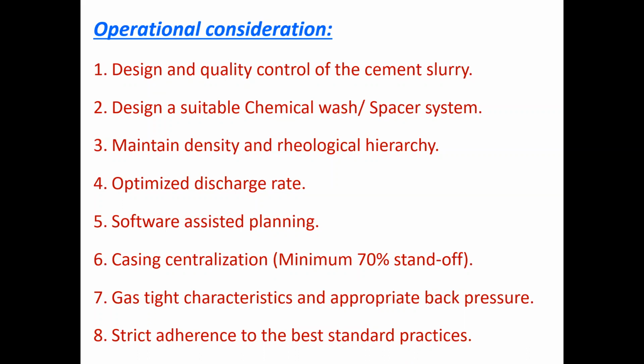There are a number of these, depending on the case; it is unique, and on a case-to-case basis the requirement decides what to use. A weighted spacer is also used. We add weighting agents because I need a spacer density higher than that of the mud, so I add barite and some other weighing additive. Suppose my spacer density is of the order of 2.2. Just by mixing barite, I will not be able to make it. In that case, I will have to add much heavier additives like Micromax or hematite in the spacer.